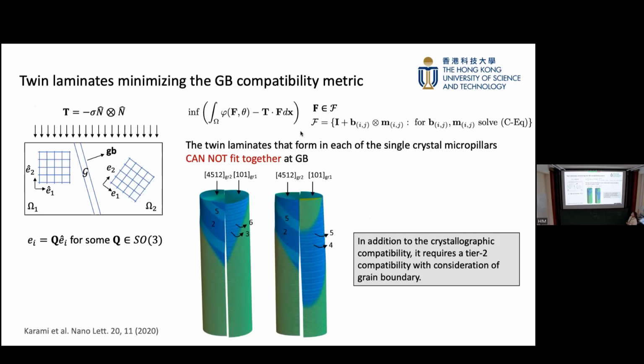First of all, let's do a very stupid and brutal minimizing of that total free energy. If we have all the compatible twin laminates in this set, we find which one can minimize that energy for one orientation, and which one can minimize for the other orientation if we have a bicrystal with the grain boundary inside. Of course, we can use EBSD or some other experimental approach to map the orientation of one grain relative to the other by some rotation matrix. So we know this. And then we find it doesn't fit.